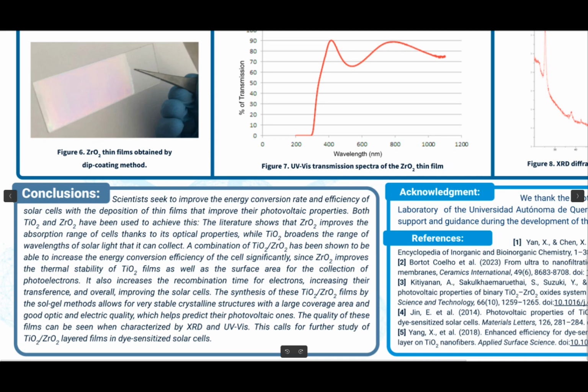While zirconium dioxide improves the absorption rate due to its optical properties, titanium dioxide broadens the range of wavelengths of solar light that the cell can collect. A combination of both of these increases the energy conversion efficiency significantly, due to the zirconium dioxide layer providing the titanium dioxide with more surface area to collect photoelectrons, effectively increasing their recombination time and transference of electrons. The sol-gel method allows for the synthesization of very stable crystalline structures. This is shown when the films are characterized by X-ray diffraction and ultraviolet-visible spectroscopy. For these reasons, more research should be made into the titanium dioxide/zirconium dioxide layer films in dye-sensitized solar cells.